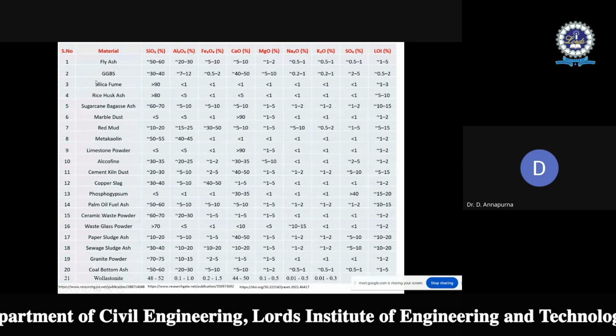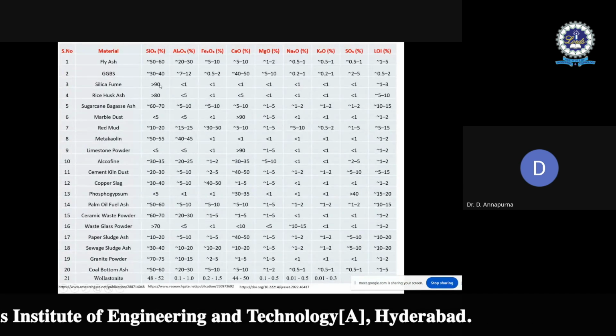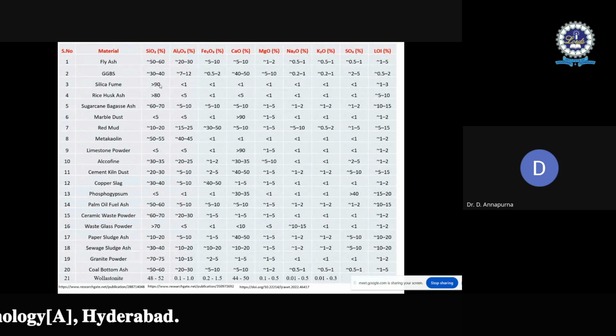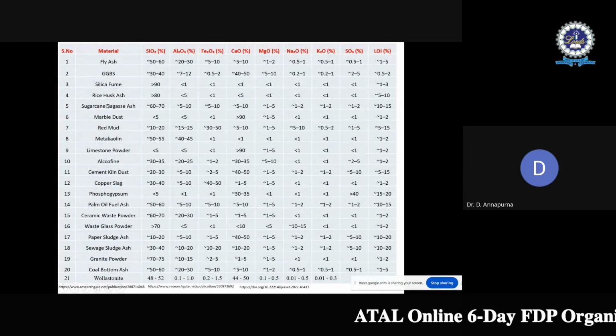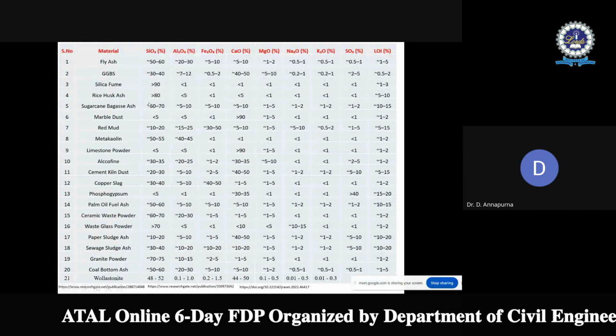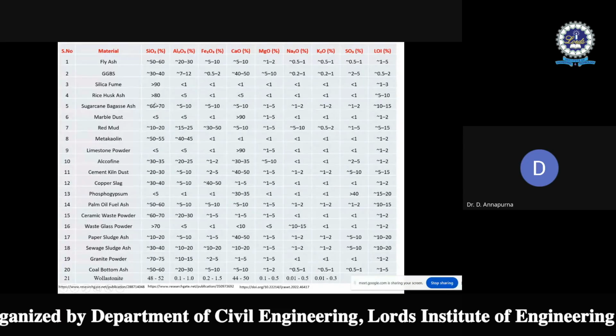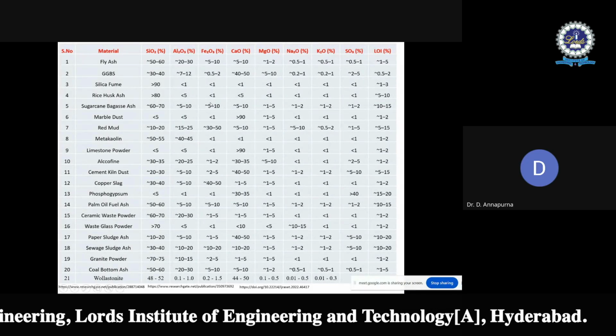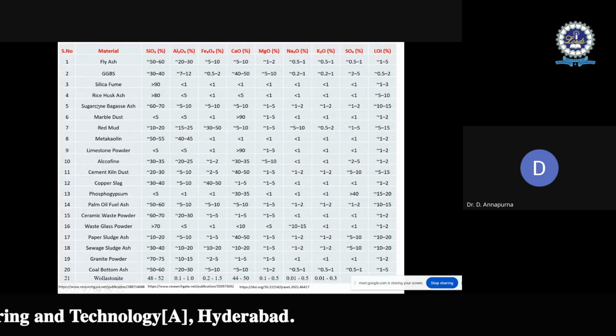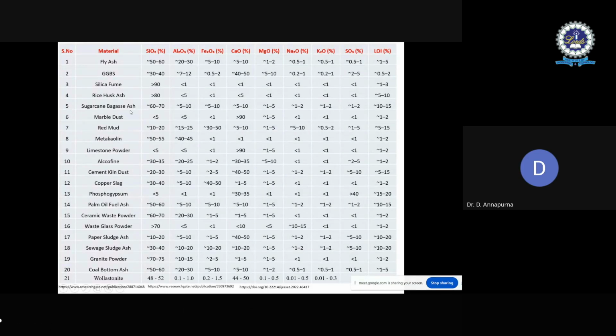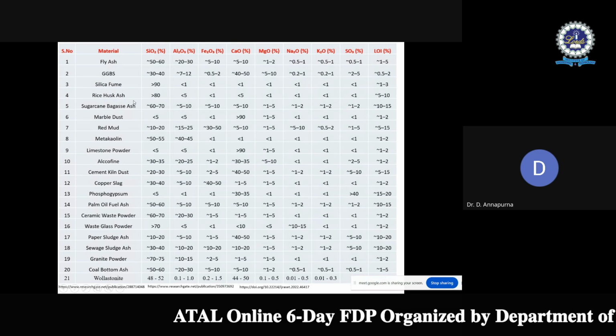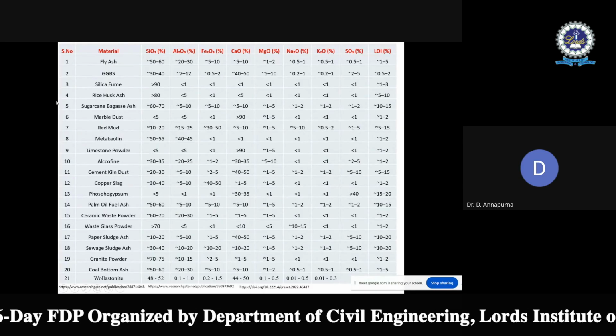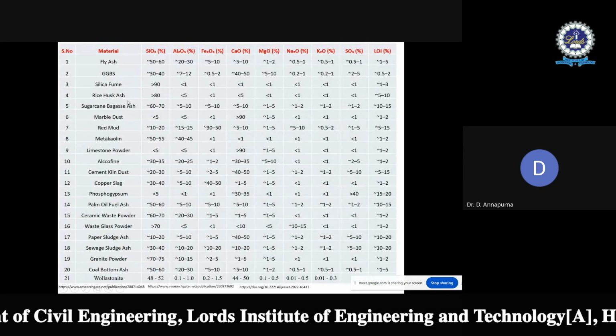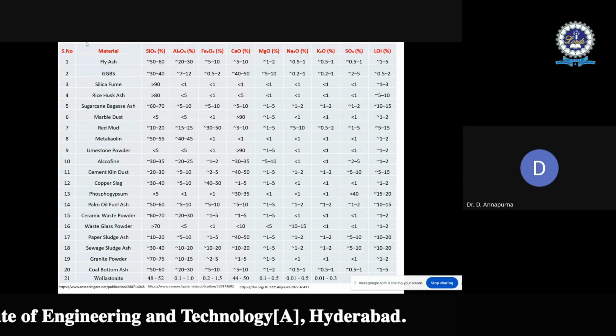Silica fume has a very high amount of silica content, mostly more than 90%. Rice husk ash will have more than 80% silica, and sugarcane bagasse ash has 60 to 70% silica along with alumina and iron oxide, because rice husk ash and bagasse ash are both agricultural waste products. Nowadays, so much research is being done in this area to make use of supplementary cementitious materials in the preparation of concrete. So there is scope to include these materials even in geopolymer concrete.